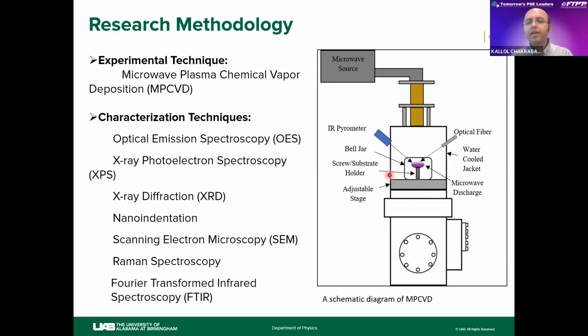We can measure the temperature of the substrate or coating with this IR infrared pyrometer, and we can also measure the optical emission spectroscopy of this plasma using the optical fiber. So this is the chamber I have used to synthesize different materials using chemical vapor deposition.